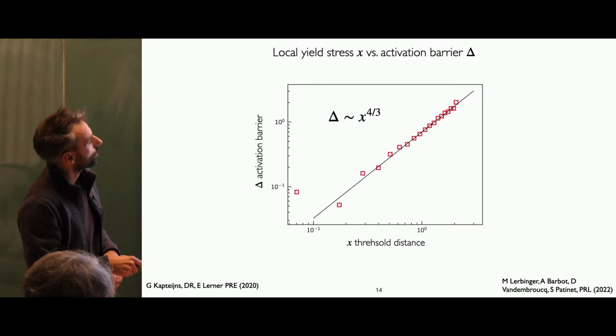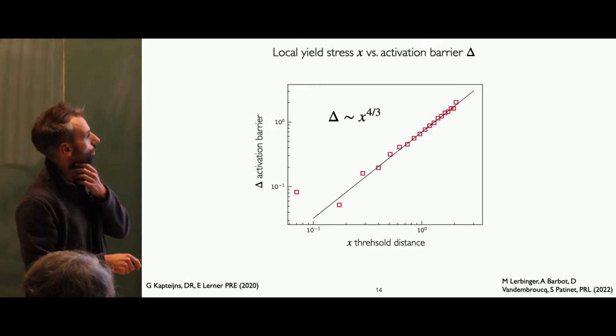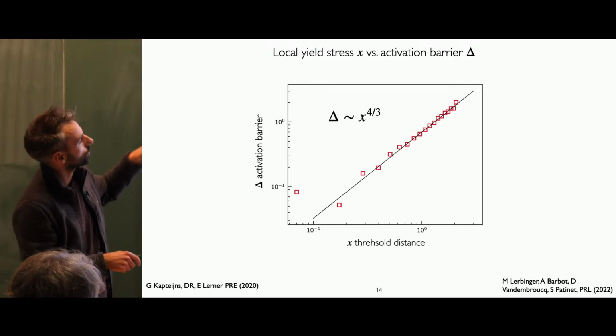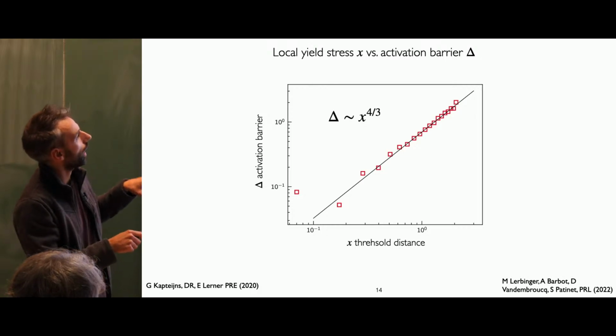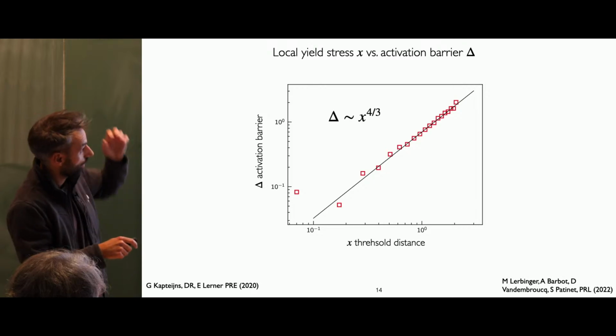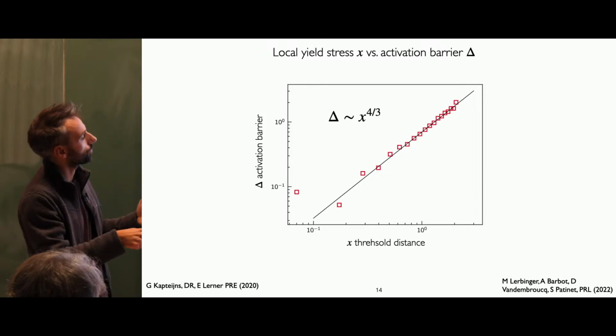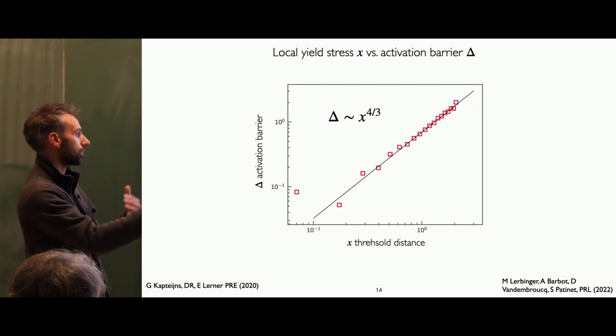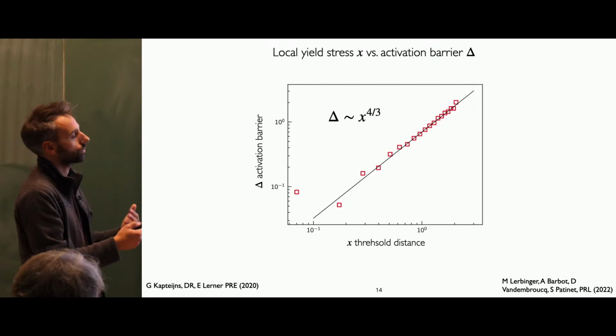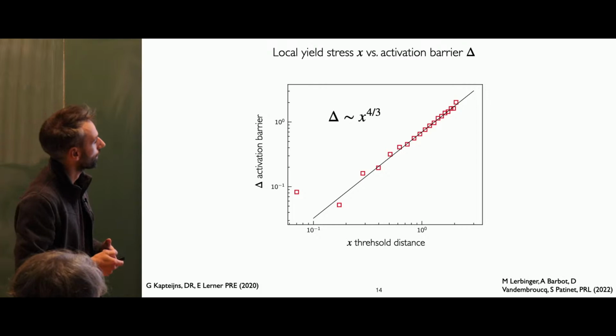And this, Sylvain will probably talk a bit more about tomorrow, but this formalism is also linking the height of the activation barrier with the distance to threshold, which will be a relation of 4 to the 3. And this makes a connection between stress, strain, distance to threshold, and activation barrier for viscous dynamics, for example.